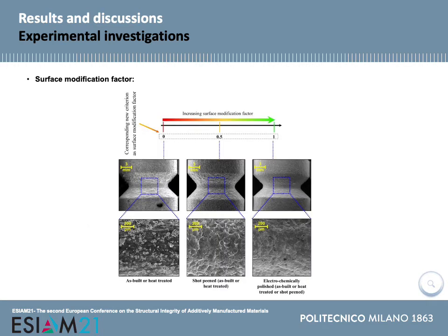In this study, for the first time, a parameter as a surface modification factor is described. Here we can see the comparison of the surface morphology in the as-built or heat-treated state, in the shot peened, and also in the electrochemically polished. You can see the surface quality is increased from as-built to shot peened and shot peened to electrochemically polished.